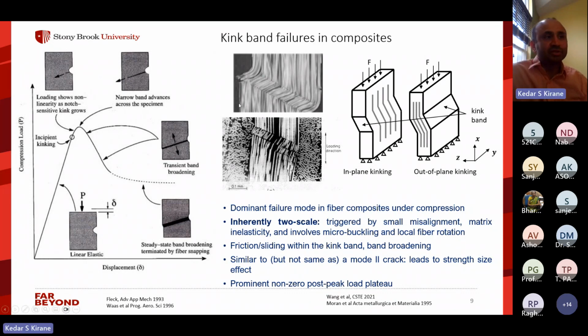So there are all these features involved in this failure mechanism. It's a two-scale effect because it is triggered by matrix inelasticity. It involves fiber microbuckling, so there is a lot of local rotation. So in that sense, it is also a strain localization problem, except the localization is interesting here because this is all shear deformation in the kink band. And outside the kink band, it is all compressive strain. So the localized region is undergoing shear, while the outside region is under compression. So then there is all this two scale effect.